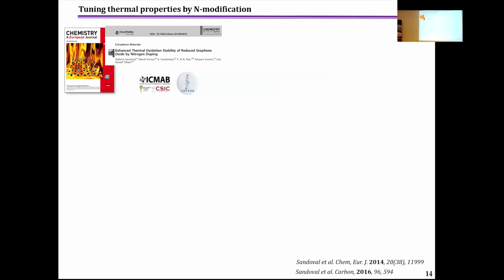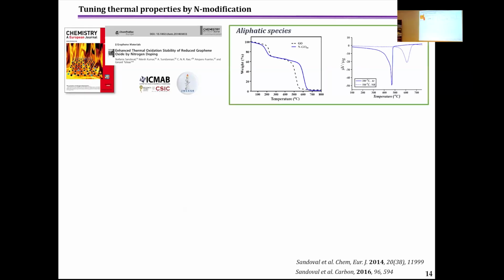About the properties we provide to the materials. This work was published in 2014, and here we highlight the ability of nitrogen to provide thermal stability to the system. Already in the sample where we introduce only aliphatic species, we see an increased thermal stability of the material. The first fall corresponds to the presence of aliphatic groups, but in this case, the fall corresponds to the combustion of the skeleton of the material. By introducing nitrogen into the system, we are able to increase the thermal stability of these monolayers.